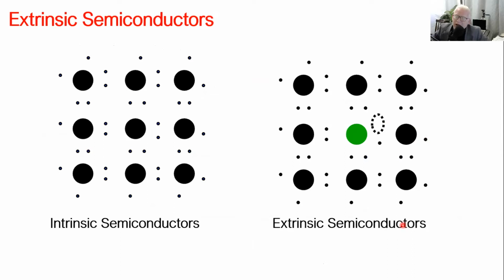Again, the same procedure. You will kick out the silicon atom by a massive force, in what we call ion implantation, one of the methods that we can use for doping. And then we replace this atom by an impurity atom, a foreign atom. This new atom, the green one now, is a third group atom. I mean, it has only 3 electrons in the outermost energy level. So 3 electrons were combined with 3 neighbors, and 1 neighbor is left alone.